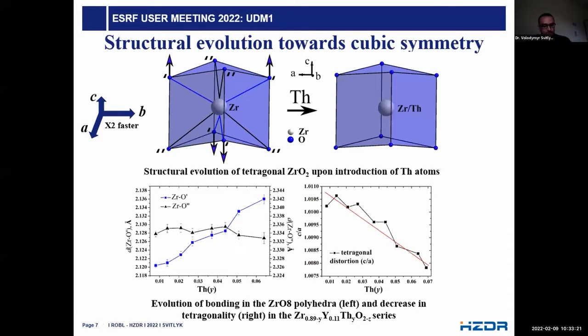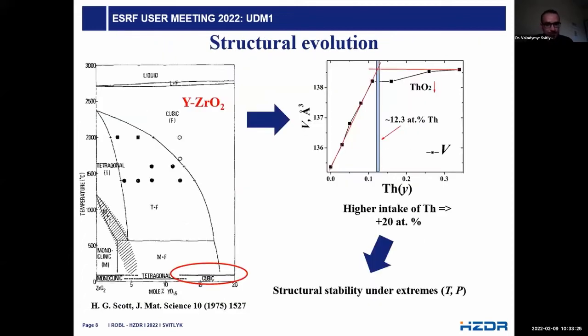Of course, it is obvious to try to introduce thorium into cubic yttrium-stabilized zirconia. This is what we did for yttrium-stabilized zirconia with high yttrium content. And indeed, we found that cubic phases can incorporate 20% more thorium.